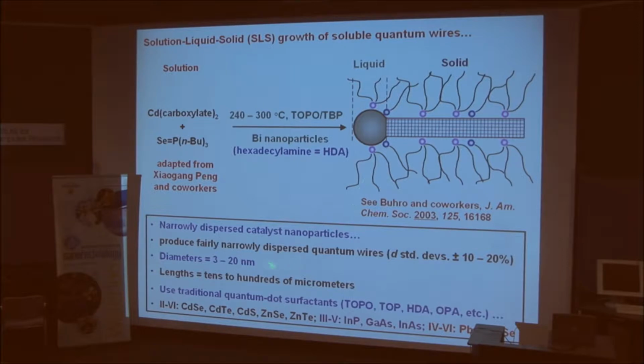And we can now grow fairly narrowly dispersed quantum wires with diameters in the range of 3 to 20 nanometers. In fact, we can grow outside that range on the high end, but there's not much excitement in terms of quantum confinement at these larger diameters. Our lengths are tens to hundreds of micrometers, depending on the case. And we use, as I mentioned, the traditional quantum dot surfactants. We can now grow a very wide range of materials in the II-VI family, the III-V family, and the IV-VI family.